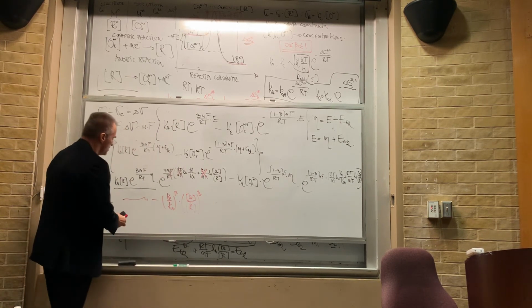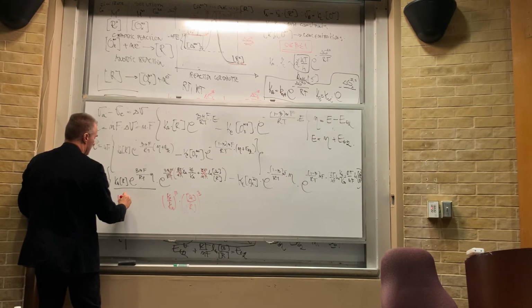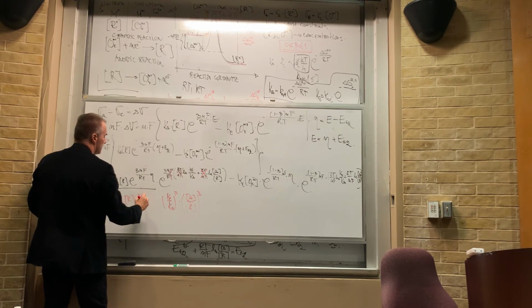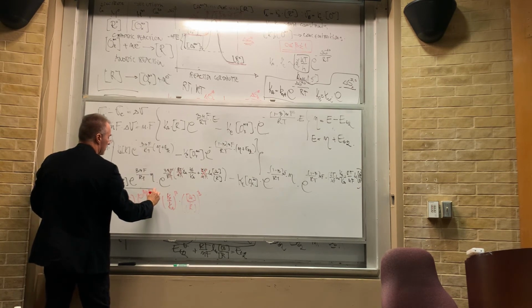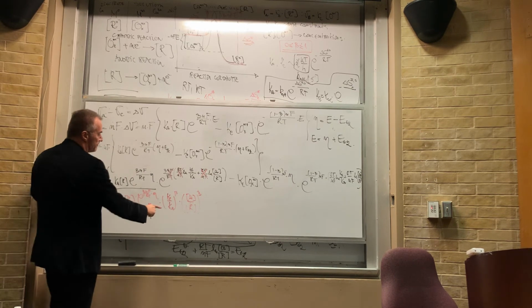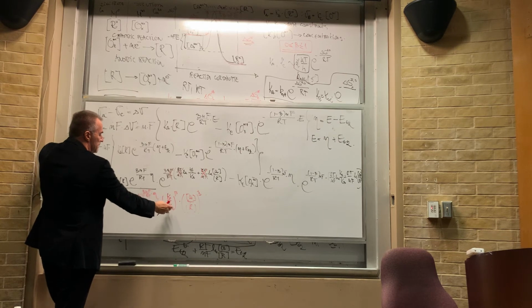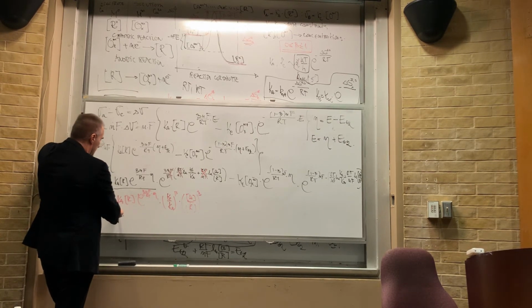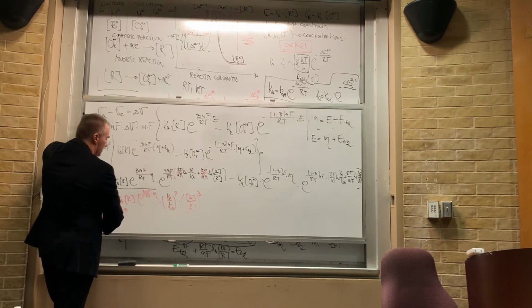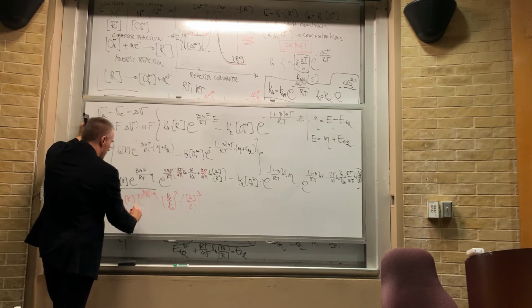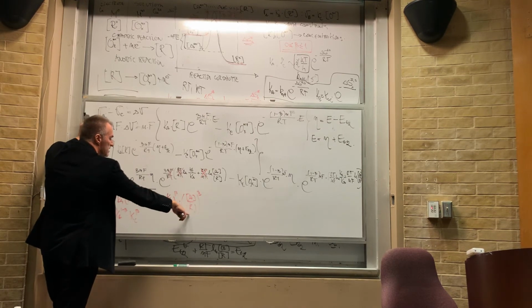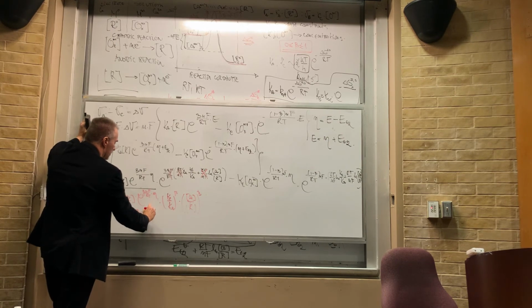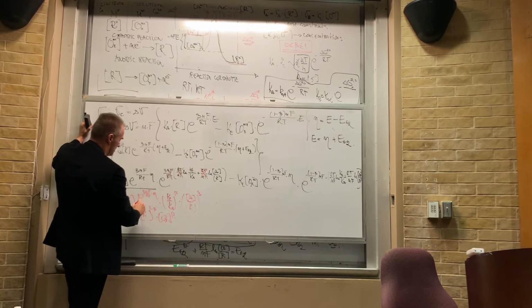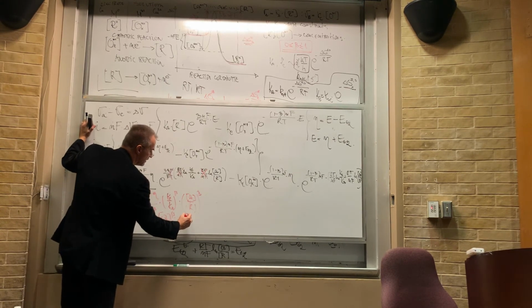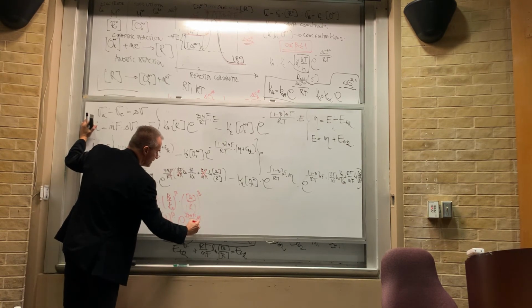Now what I really want you to pay attention to here is that I have Ka, the concentration of the reduced species, times e to the beta nF over RT over potential. And this multiplies this one here. Now, look at this. Ka here is in the denominator, which means basically Ka is the 1 minus beta. And this Ka here, you end up with Ka to the 1 minus beta, right? Then you have Kc to the power beta. Then you have R, and this is R to the minus beta, so it's basically R concentration to the power 1 minus beta. And then you have the oxygenated species to the power of beta. And then you have this term here, which is e to the beta nF potential over RT. Okay?